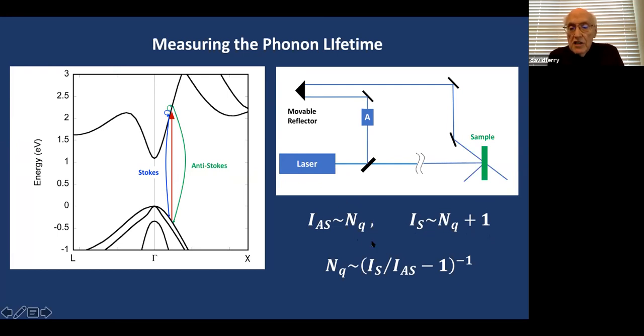Now I can look at these and take this ratio, IS over IAS minus 1, invert it, and I get a guess at what NQ is. So I can measure this as a function of the momentum of the photons coming in, and therefore get the distribution function and the amplitude. And Raman scattering is done this way.